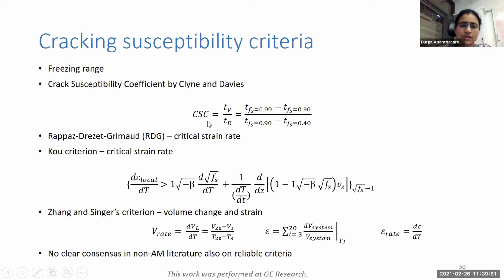If we look at the literature, we see that there are several criteria that are proposed, starting from something as simple as a freezing range. Then there is the crack susceptibility coefficient by Clyne and Davies, which looks at the time spent in the last part of solidification, from 90 to 40%. These are more empirical correlations. Something more related to the critical strain rate is then proposed by the RDG model or the Kou criterion, which looks at the shrinkage effect and then the overall stresses in the system, and if a critical strain rate is reached, then there is a crack forming.